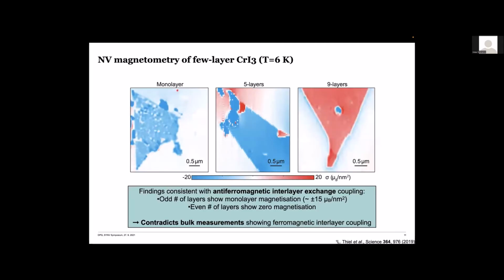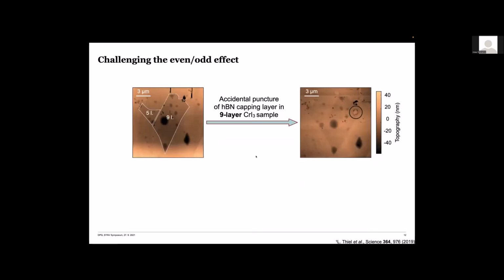All right, so we carried on and looked at a range of samples, and it was all confirmed in the sense that, for all the odd number layers, we saw a magnetization which was non-zero and identical for all these samples, whereas all the even numbered layers showed zero stray field and 0 magnetization. So this question of this even odd effect in fact persisted, and for some time we were still puzzled by that. Now, luckily, there was an accident in one of our experiments, which allowed us to shed some more light on this issue. And the accident was as follows.